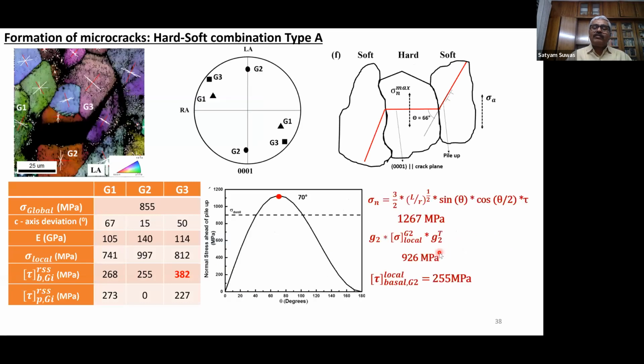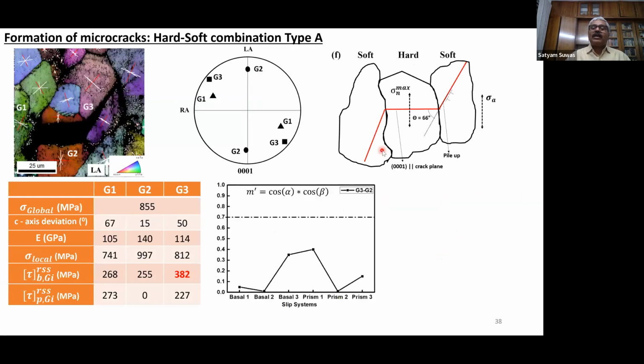So then we tried to model it with the Stroh model, to see whether this soft-hard grain combination works or not. Particularly this orientation was seen here, and the slip traces were examined, and this is particularly a crack, right? So these grains G1, G2, G3 are mapped here in the pole figure. We could see very clearly the C-axis deviation between G3 and G2, there is a separation, right? The crack is between G3 and G2. So we could see here 50 and 15, right here.